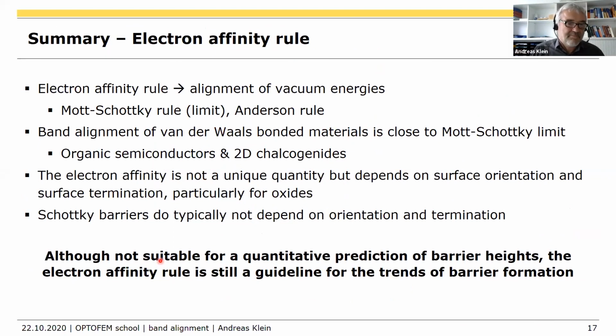If you have an N-type, if you take a metal with a high work function, your Fermi level will be higher than if you take a metal with a low work function. That's for sure true. But it's not quantitative, and for many reasons. So you cannot take work functions of a material in order to predict the barrier heights. This doesn't work. Actually, I was once asked, what's the work function of titanium dioxide? In principle, that's not a reasonable question because it can be something between 4 and 6 electron volts, depending on how you prepare your surface.